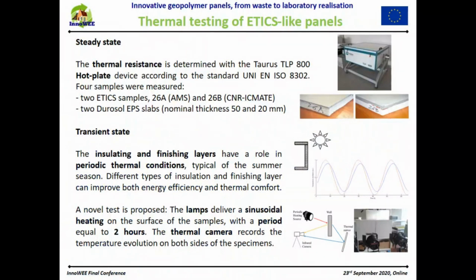We tested also the thermal behavior of ETICS panels in two ways, steady state and transient state. In steady state, we measure the thermal conductivity with the standard method, EN ISO 8302, using the hot plate apparatus. We tested both the laboratory production from ICMATE and the upscale production from AMS. For the transient state, instead, we proposed a novel test. As the finishing layer has a role in the dynamic thermal conditions that are typical of the summer season, we wanted to investigate this behavior. So on the bottom right, you can see a thermographic setup for the measurement, where we use lamps to simulate the thermal stimulus of the sun, and we record the surface temperature of the panel during a test.